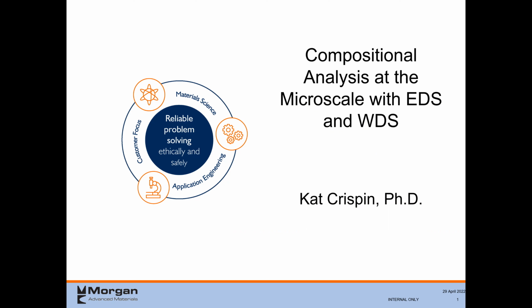And WDS is somewhat similar, right? You do a similar kind of thing, but you get a lot better sensitivity. Yes, we have a lot better sensitivity with WDS. With WDS, you cannot just analyze something without a standard, or you don't get anything. It just gives you counts, and that doesn't tell you anything, because we don't have built-in standards for WDS. So with WDS, the first thing you do every time you're looking for quantitative analysis is you analyze your standards and you tell it what the standards are that it's comparing to.